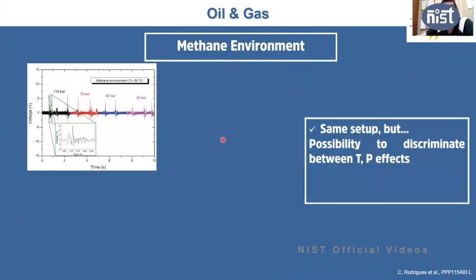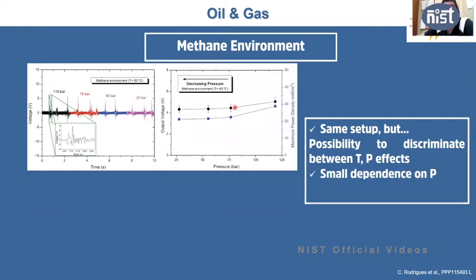We did another experiment to try to discriminate what is happening from the pressure from the temperature, and we did this with methane. So this is also a gas that comes out of the extraction wells. And in this case, because you have a gas, you can separate the temperature from the pressure. So we decrease the pressure, and as you decrease the pressure, the output voltage comes down a little, but it doesn't change very much.